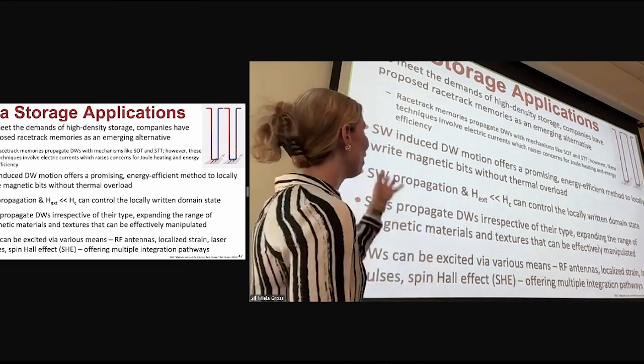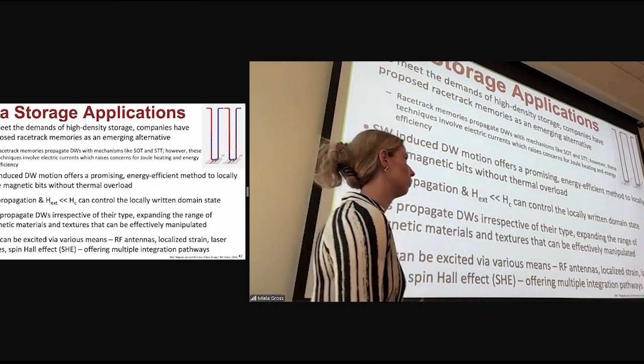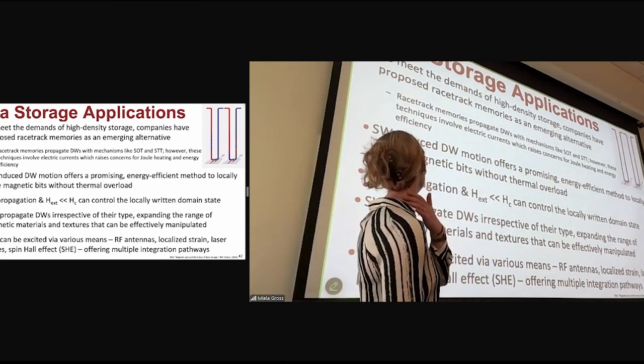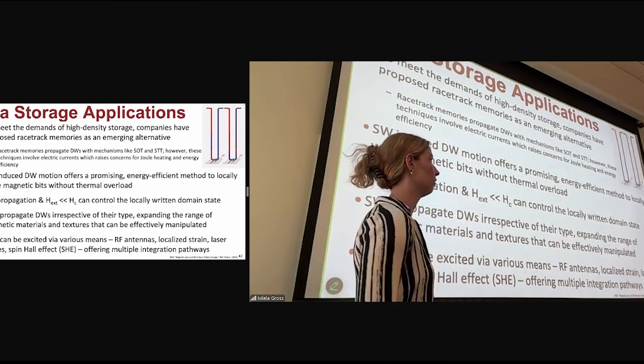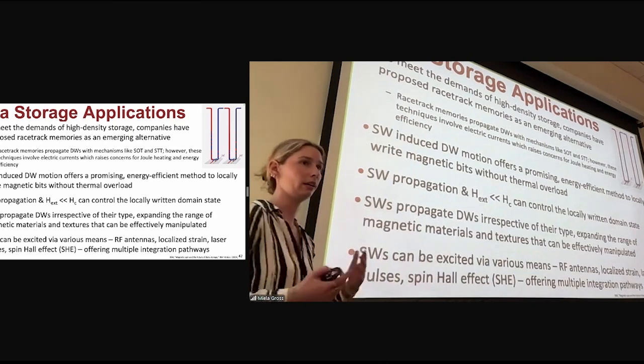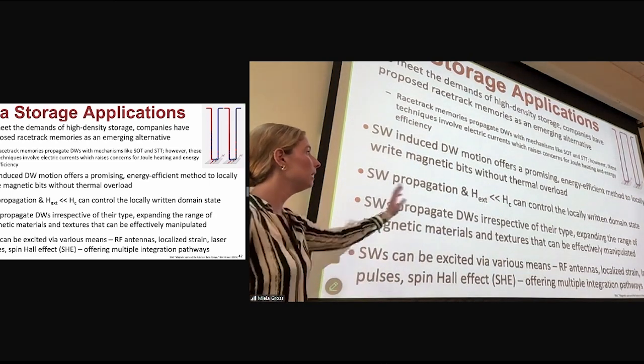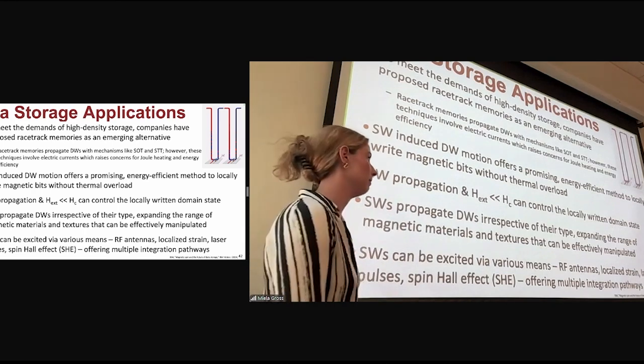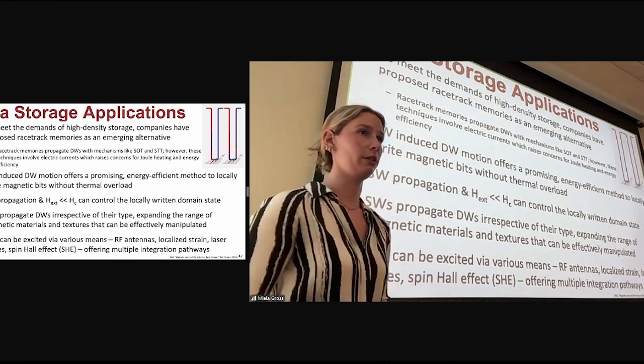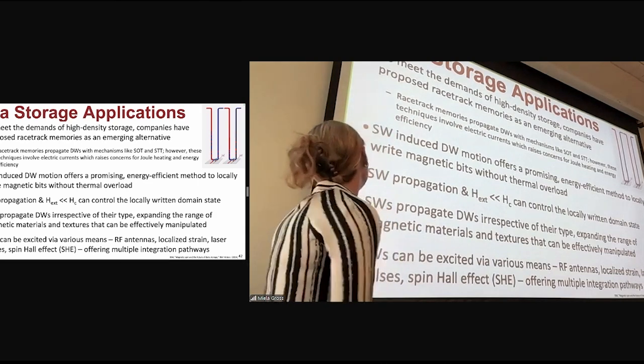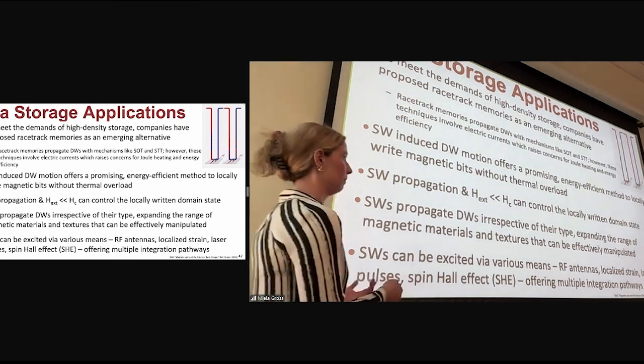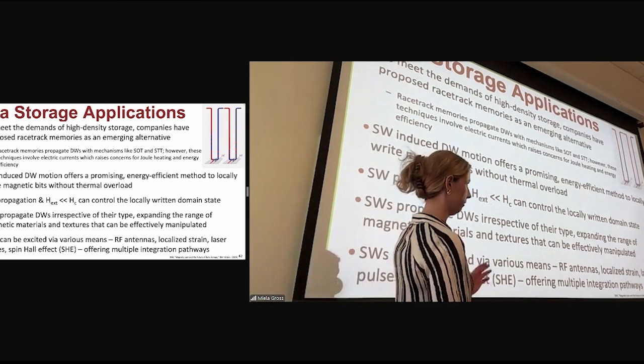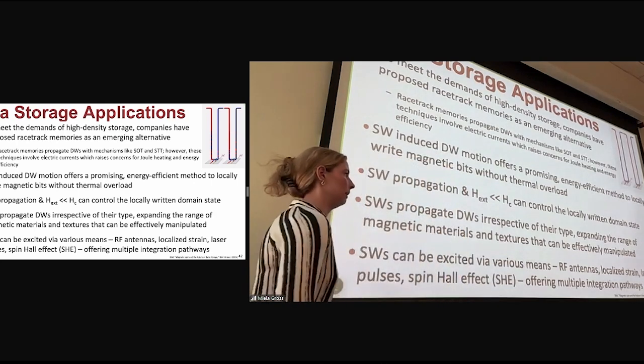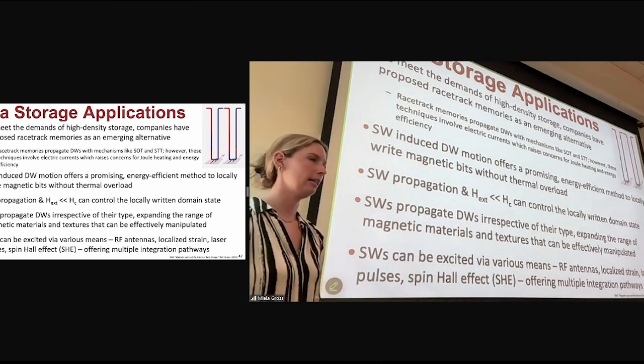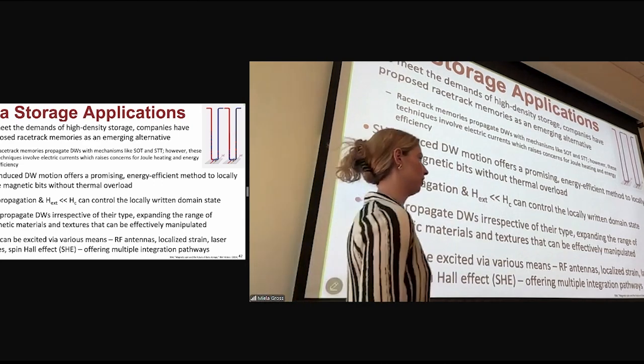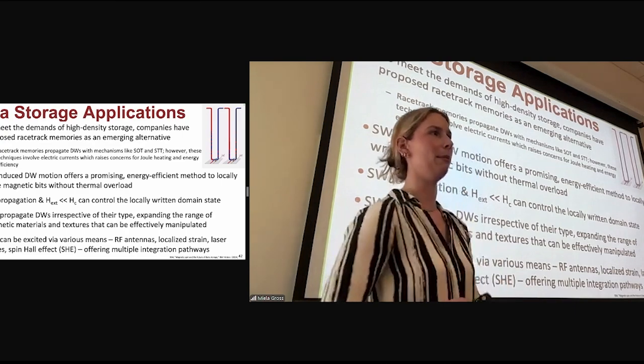They've been proposed with mechanisms like spin orbit torque and spin transfer torque. However, both of those mechanisms involve electric currents, which raises concerns for joule heating and energy efficiency, which is inherent to electrons moving. Spin wave induced domain wall motion, however, offers a promising energy efficient method to locally write magnetic bits without the concerns of thermal overload, because you don't really have anything moving. With spin wave propagation, and again, these really small external fields below the coercivity of your film, you can control the locally written domain state. And spin waves propagate domain walls irrespective of their type, we found, and that expands the range of magnetic materials and textures that can be effectively manipulated in this kind of racetrack memory.